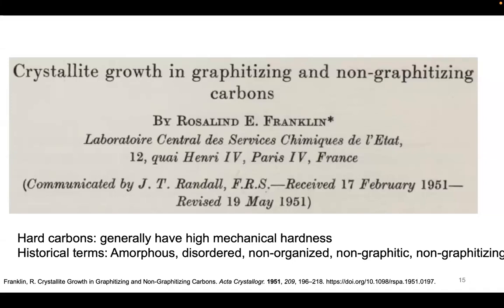Now, what you may have also seen in terms of the terminology, and it can be quite confusing, I think, when you're reading, especially older papers, there's a lot of references to hard carbon, but they've also been deemed as amorphous carbon, disordered carbon, non-organized. The history of hard carbon, non-graphitic, we've seen that. Non-graphitizing, we've seen that as well. But generally it is carbon materials that have high mechanical hardness, hence hard carbon, that are non-graphitizable, right? And so that's different than that of graphite that we've talked about for lithium-ion battery materials, because the sodium ions are larger, and thus, they have to be accommodated differently than just the use of graphite.